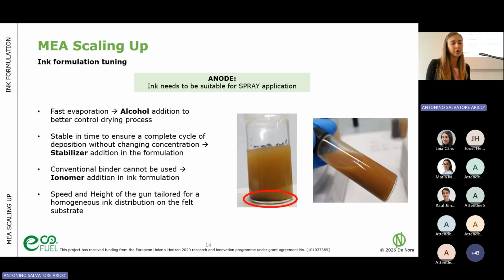And also, we need to ensure that the ink is stable for a proper amount of time, because if we think about the lab scale, that is the air gun, just doing a spray on a small area, we keep our ink stirring during the time of the deposition, we take an aliquot and spray, no problem. But if we are using the automatic spray coater, the ink just stays there for the whole time of the deposition. So it really is necessary to be stable, otherwise we get a gradient of concentration and also clogging, because we have particles that are depositing. So that was the problem. So we need to work on a proper stabilizer in the formulation.